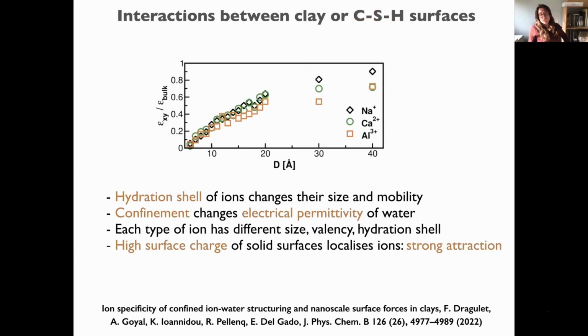Another way to understand this, and bring it to a more theoretical model, is to compute the electrical permittivity of water in confinement. Here I'm showing a curve where, with different ions confined between two charged surfaces, the dielectric constant deviates from the bulk value, especially at very small distances.